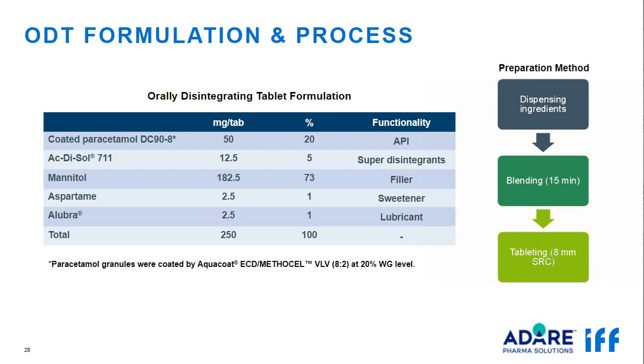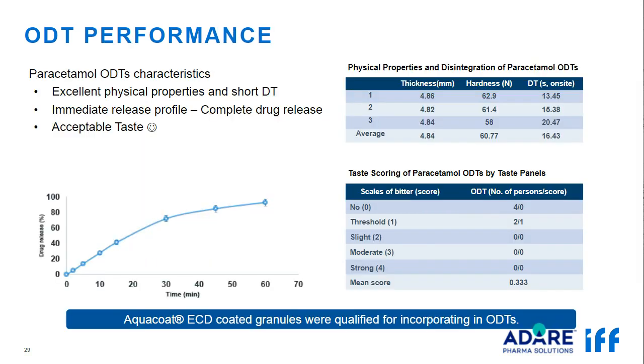Next, the coated paracetamol granules were evaluated in an ODT formulation. The coated granules and the functional excipients shown in this table were incorporated into the ODT formulation using a simple direct compression method. The resulting paracetamol ODTs were evaluated for physical properties, disintegration time, drug dissolution, and taste masking performance. The study showed that the tablets had a short disintegration time of less than 30 seconds, full immediate release, and acceptable taste based on evaluation by a tasting panel. The evaluation confirmed that the coated granules were qualified for application in ODT formulation.